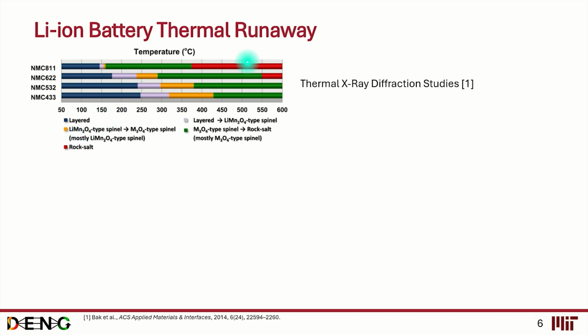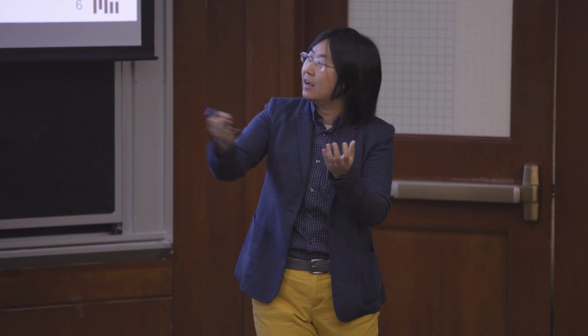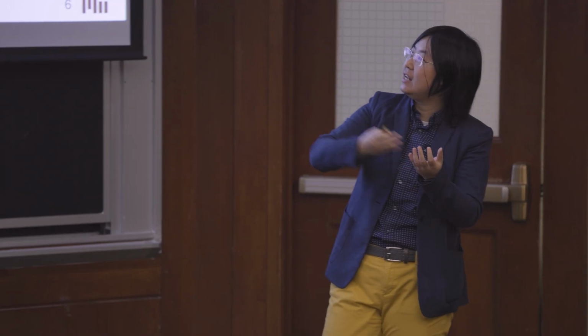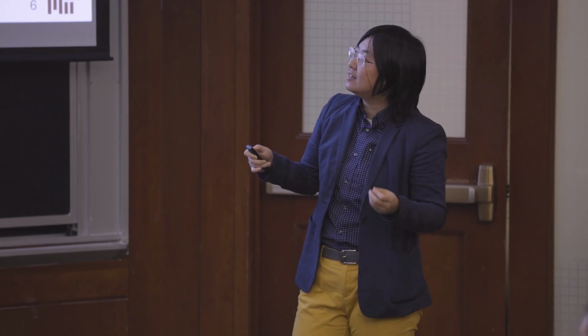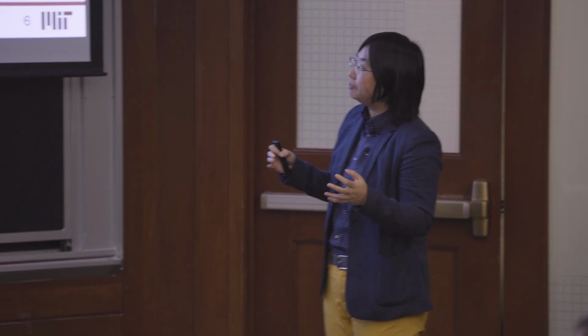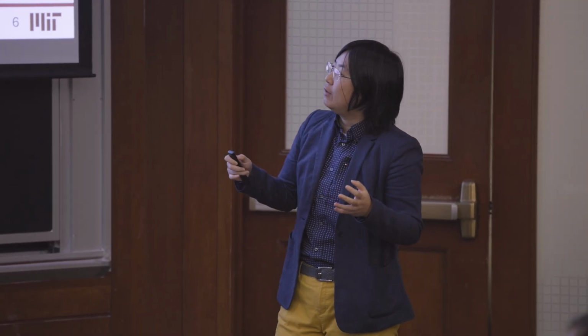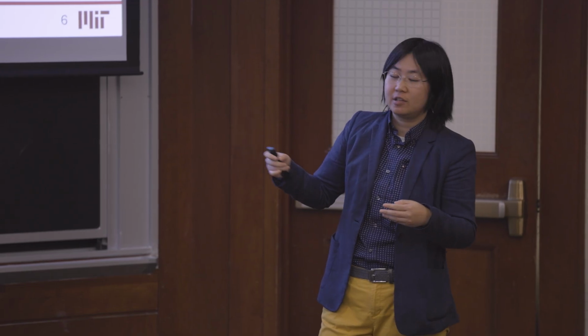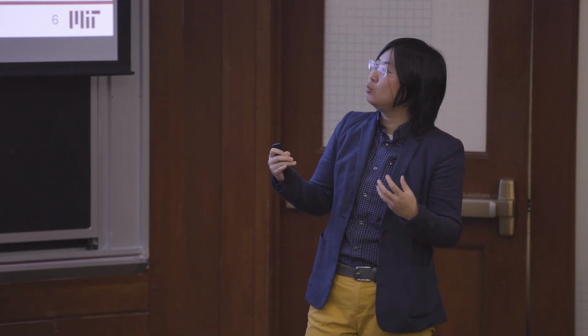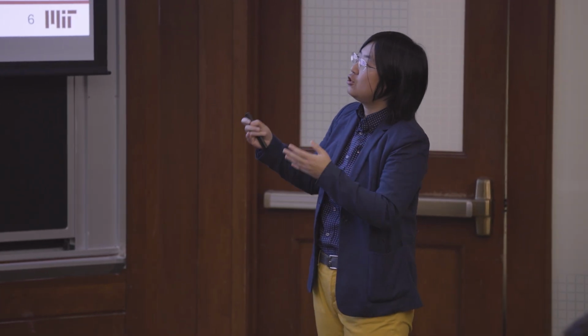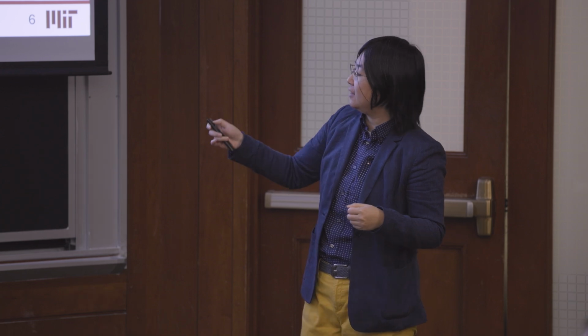Basically, you can see that they would thermally decompose at different temperatures, but there is also a shared trend. For example, the materials by design should be layered structures such that lithium ions can go in and out of the lattice to store energy and electricity, right? As we increase the temperature, the lattice would transform eventually to the rock salt phase.